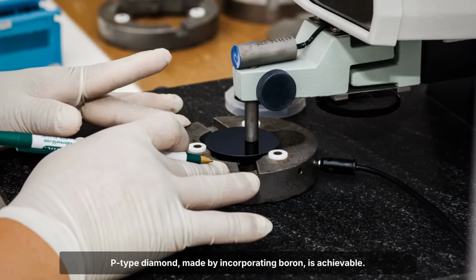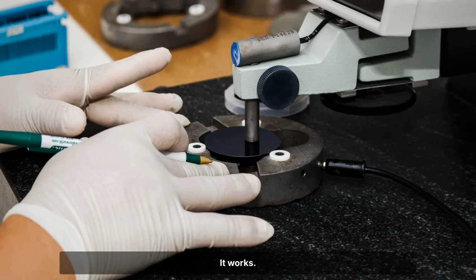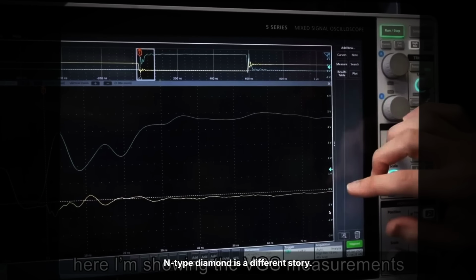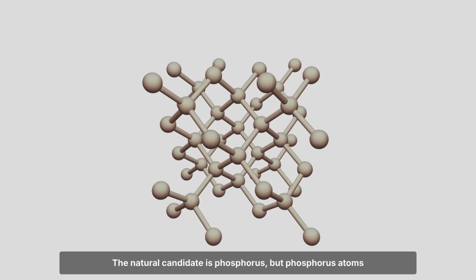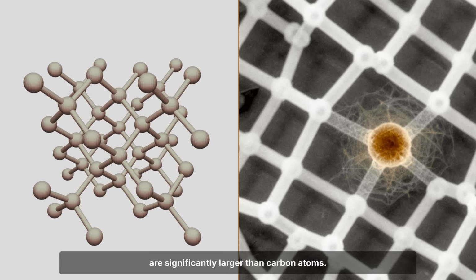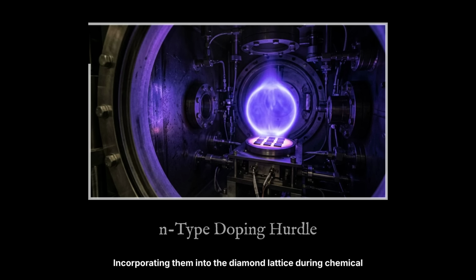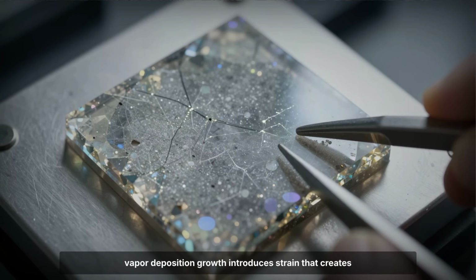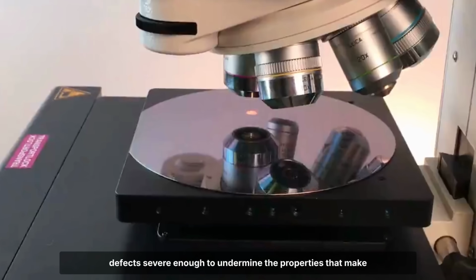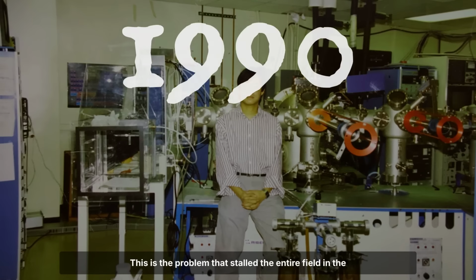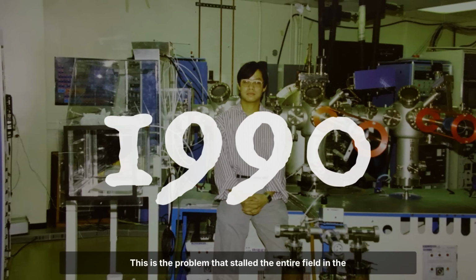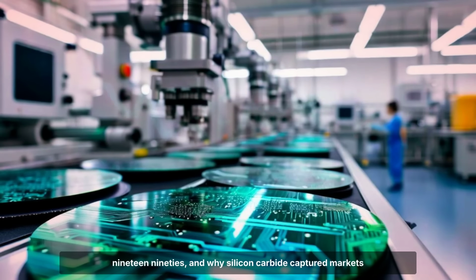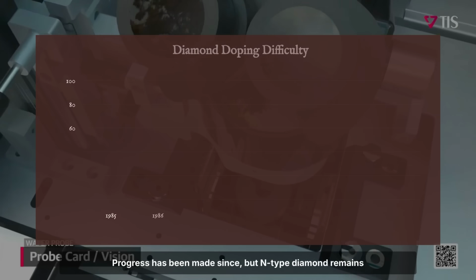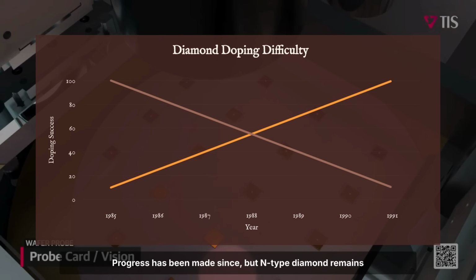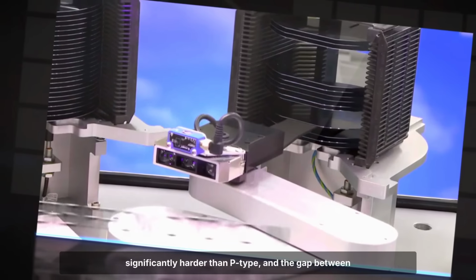P-type diamond, made by incorporating boron, is achievable. It works. N-type diamond is a different story. The natural candidate is phosphorus, but phosphorus atoms are significantly larger than carbon atoms. Incorporating them into the diamond lattice during chemical vapor deposition growth introduces strain that creates defects severe enough to undermine the properties that make diamond worth using. This is the problem that stalled the entire field in the 1990s, and why silicon carbide captured markets that diamond was supposed to own. Progress has been made since, but N-type diamond remains significantly harder than P-type, and the gap between laboratory demonstration and reliable manufacturing is still wide.